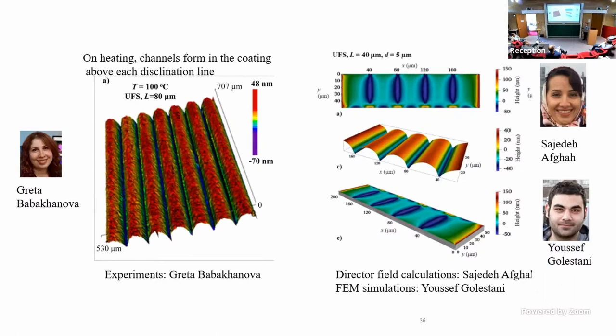But what we've shown is that the new edge will look exactly the same. It's just from the free surface elastic relaxation. So even if you cut off this bad part, a new bad part will form. So if you want the material to have channels that cut all the way through, you're going to have to clamp it some other way.